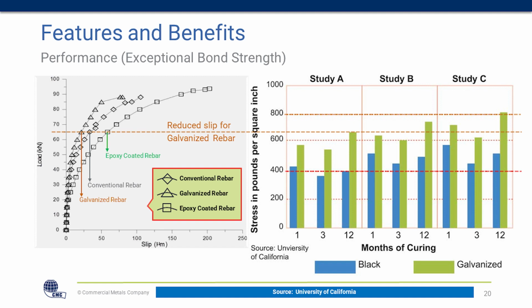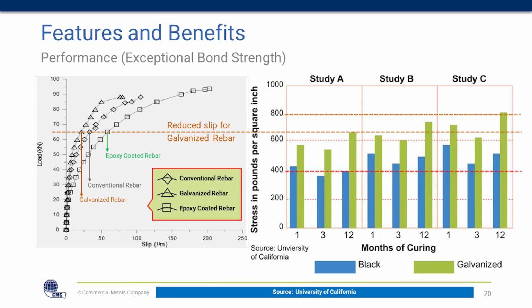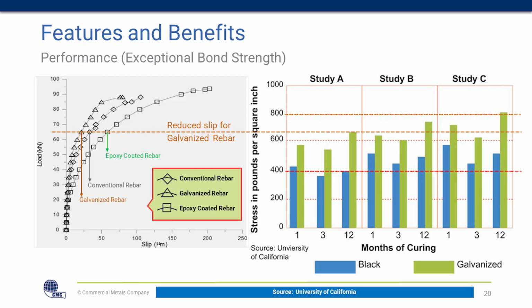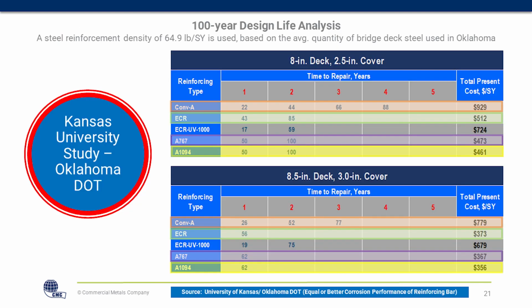As far as bond strength, may have mentioned that already, but you see this is an excerpt from a University of California study. There was over a 12-month period, and they did 3 measurements, one at 30 days, 90 days, and another one at 1 year. And what you see happening here is the galvanized material, as it's curing, that bond strength is actually improving, and the slip resistance is superior to not only the epoxy coated rebar, but also conventional rebar as well.